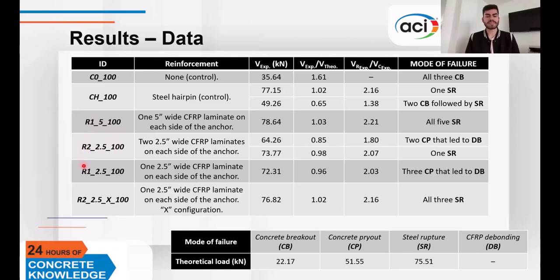On the other hand, specimens with just half of the reinforcement always showed this last type of failure mechanism, a concrete pry-out that generated the debonding of FRP sheets. Their behavior in general was similar to that of the specimens with total area with two laminates on each side, implying that the outermost laminates did not receive a significant force. This idea is supported by their unit strain behavior and theoretically by their strut and tie model.